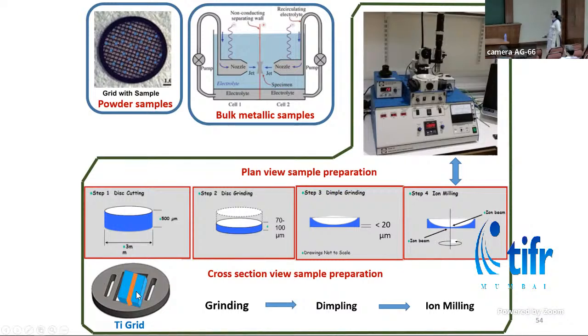If we have a thin film and want to image the cross section of the sample, then we cut the films into 0.7 by 1 mm pieces. We make a sandwich of them, and that sandwich is put into the titanium slot grid. This titanium slot grid is processed in this route again to get a final TEM sample.